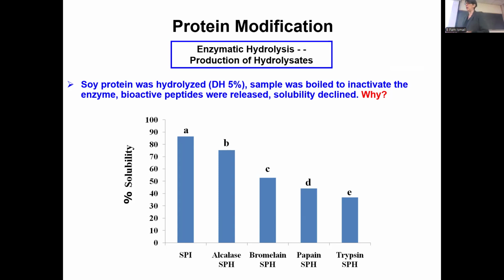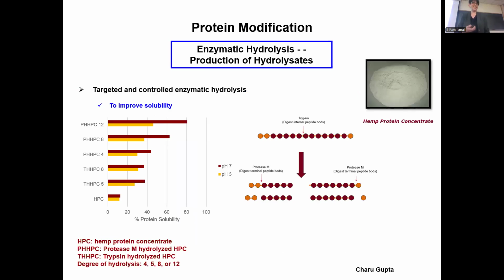The type of enzymes that we were looking at, all of them are endoproteases. So they really chopped that protein, broke it open, exposed hydrophobic interactions. So with heat, we lost solubility. So the problem is because of the heating? Yes. Heating caused the hydrophobic effect? Yes, yes, yes. Would the inactivation also affect the solubility? There is no pH treatment that will completely inactivate the enzyme without thermal treatment. So even if you try to do acidic inactivation, you need a lower temperature, but you still get it.